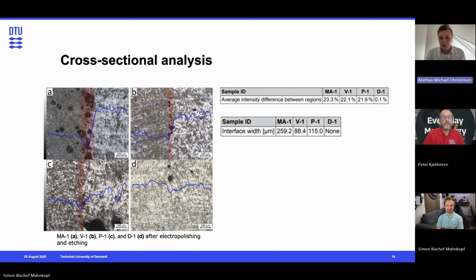Yeah. Another thing that was also very interesting in our work was, yes, we managed to get it to work, and we managed to get this volumetric slicing where we go across the part and then we ramp the power up to promote each phase region. But what we also discovered was the difficulty in metallurgy prep of this part, because you have a metastable austenite. So just being able to cut and grind it as you do in metallurgical sample prep is not quite as easy as you would think.